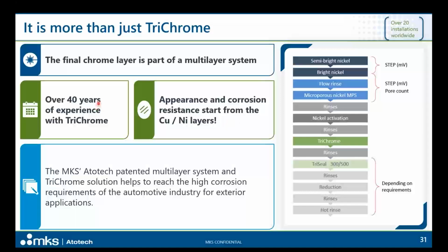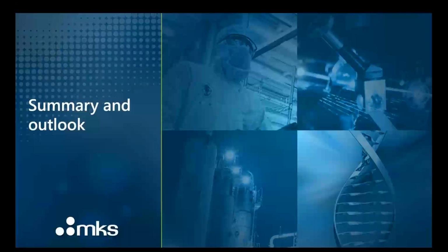So at MKS Atotech, we have over 40 years of experience with trichrome, and our patented multi-layer system and trichrome solution will help you to reach the highest corrosion requirements of the automotive industry for exterior application, to also help achieve different thicknesses, and what is also very important, to do this without chrome 6 in your plating process. So now, please allow me to shift the presentation to Johnny, and he will go through the summary and the outlook.